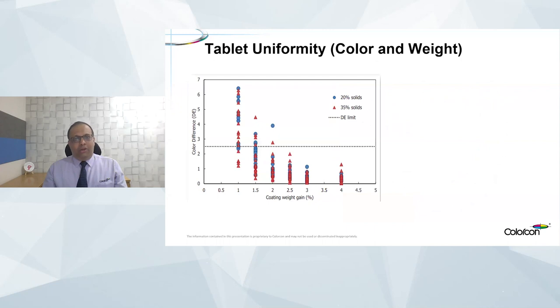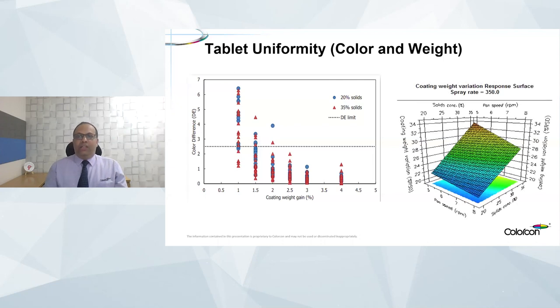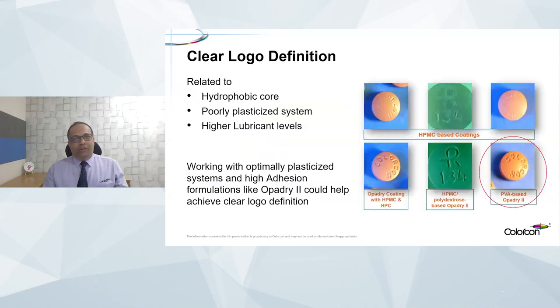For tablet uniformity, I talked about Opadry QX, which can be a higher solids coating, but it is important to have color uniformity at our standard weight gains of 2.5 to 3%. And of course, coating weight uniformity and color uniformity are going to depend on the pan speed as well as the spray rate that we are trying to achieve. So higher pan speeds, optimized spray rates, and a good opacity in the coating would ensure that even at higher solids, you would be able to get a good tablet uniformity.